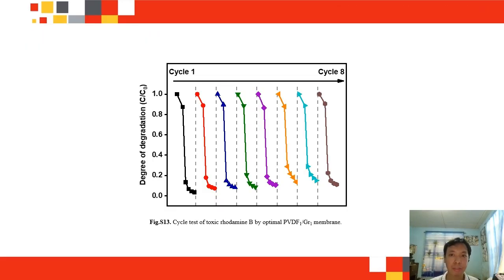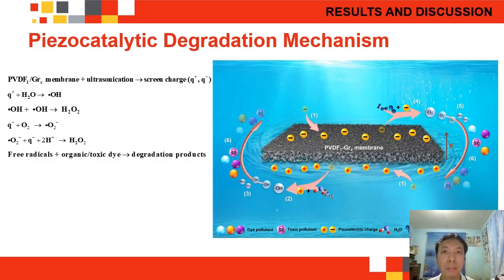For the stability test, the best performing membrane, PVDF1 graphene 1 ratio, was used. The membrane demonstrated excellent performance stability for 8 testing cycles, maintaining a degradation rate of RHB dye above 85%. Based on the previous experiment results, the potential mechanism for the piezocatalytic degradation of the toxic dye was provided in the figure. When the membrane undergoes deformation and strain due to the ultrasonic vibration or when the mechanical energy is applied, the space screening charges and the free charges are attracted to the two differently polarized surfaces of the membrane, forming a piezoelectric field to balance the change in the material's dipole moment.